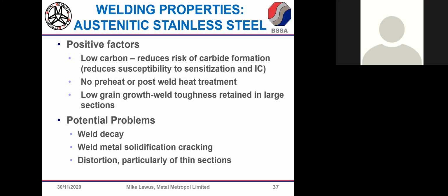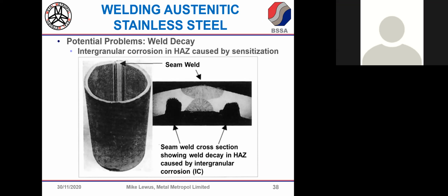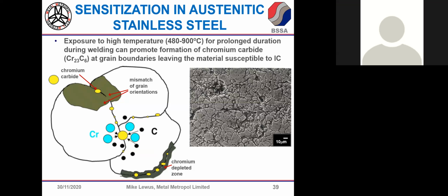So a good type of stainless steel to weld. You'll see the potential problems: weld decay, weld metal solidification, distortion. Let me quickly go to the weld decay because it touches on the sensitization issue that I just said. If we do get this chromium carbide formation, because we've heated the material up through the welding process, and subsequently it's exposed to an aggressive environment that promotes intergranular corrosion, you'll see the kind of thing we can ultimately end up with. Here we've got a pipe component. The heat affected zone has just become eaten away because the grain boundaries have been attacked and the grains have essentially fallen out. This is a schematic and a photograph of a real surface that actually was sensitized or was subject to conditions that promoted intergranular corrosion.